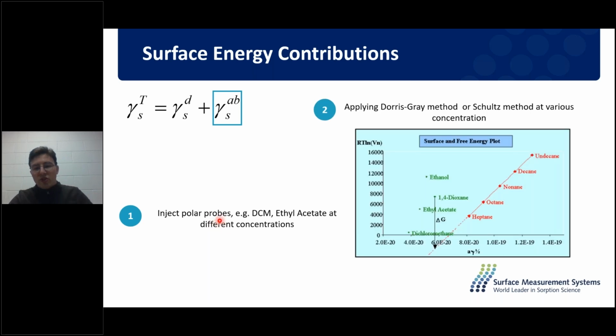Now, this similar methodology can be applied to my polar probes. Now, the distance that these probes have from my alkane line when extrapolated backwards is directly related to that additional contribution to energy that they have as a result of those polar functional groups they have on their structure. And that is how we can quantify the additional interaction they have as only a result of their polarity, with no regard for their van der Waals interaction or their dispersive interaction.